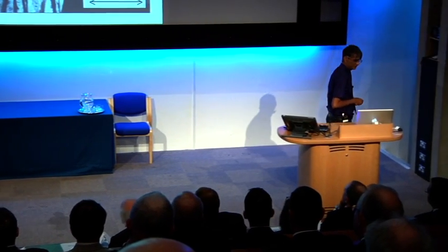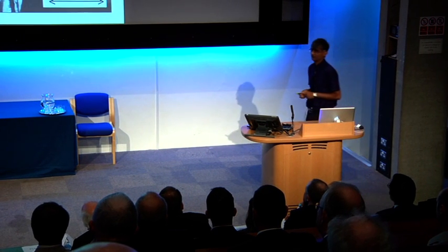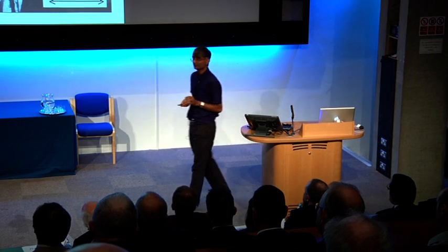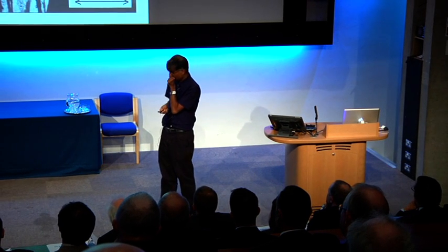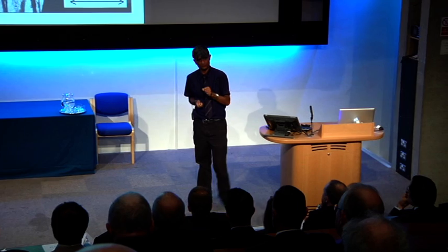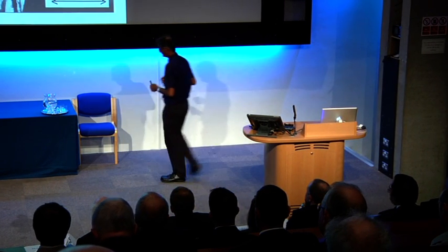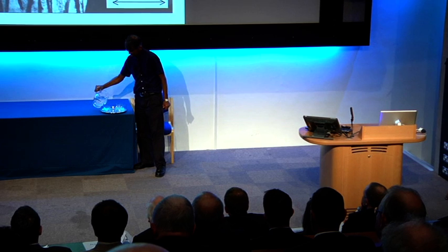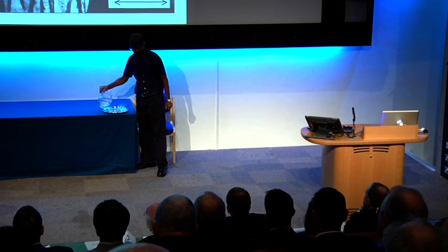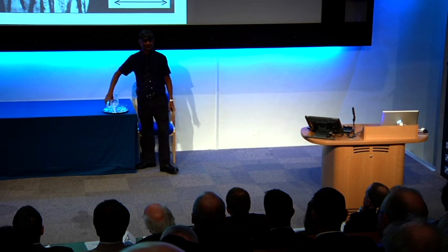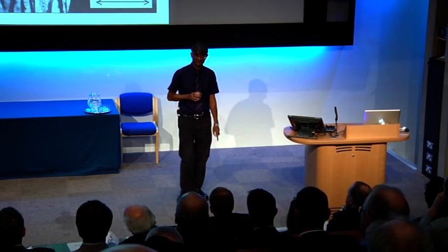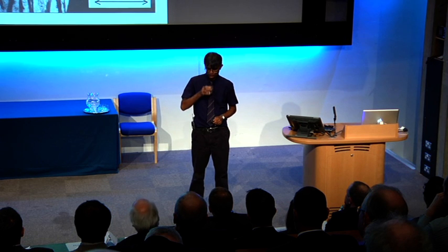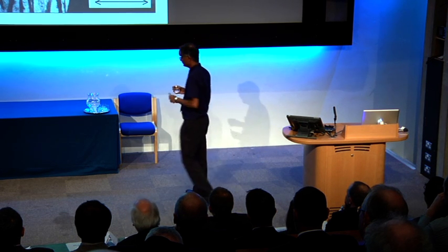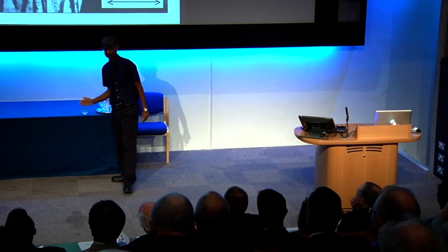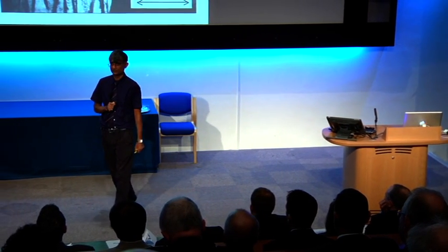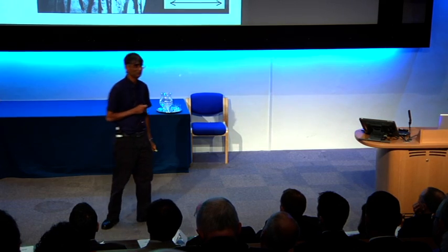But this would have a strength of the order of 1600 megapascals, so that really isn't sufficient to make a bearing. In order to make this stronger, we've got to make the plate finer. And we have a lot of theory developed over a period of 30 years, as I said, to see how we can make it finer. And one method is to reduce the transformation temperature. So the question then arises, what is the lowest transformation temperature at which I can produce bainite?